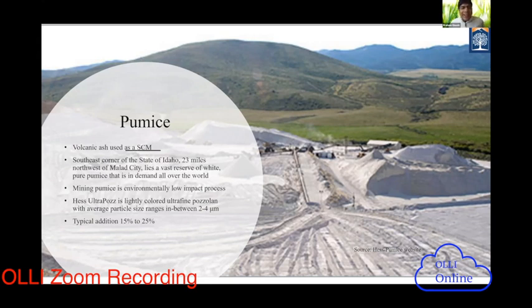These are naturally calcined materials, highly sustainable, zero CO2 emission, as you can imagine. When you replace cement with pumice and other natural pozzolans, you are reducing the CO2 emission in the concrete heavily. It's an environmentally low impact process, and that's why it's called ultra pozzolan, which is also the company name of those producing the pumice. It's a lightly colored ultrafine pozzolan, average particle size between 2 to 4 micrometer. Typically we replace cement with 15 to 25% of the pumice. That's the new material we are testing.